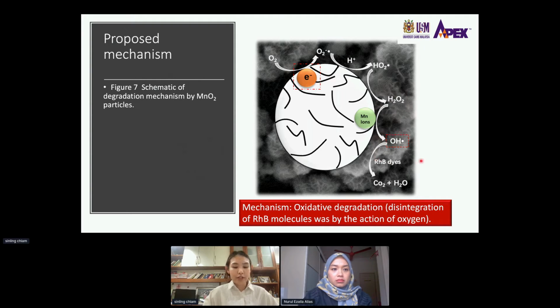As we all know, hydroxyl radicals are very effective reactive species which are able to degrade the dye into smaller molecules. So the mechanism is proposed to be oxidative degradation, where the disintegration of the RhB molecule is by the action of oxygen.